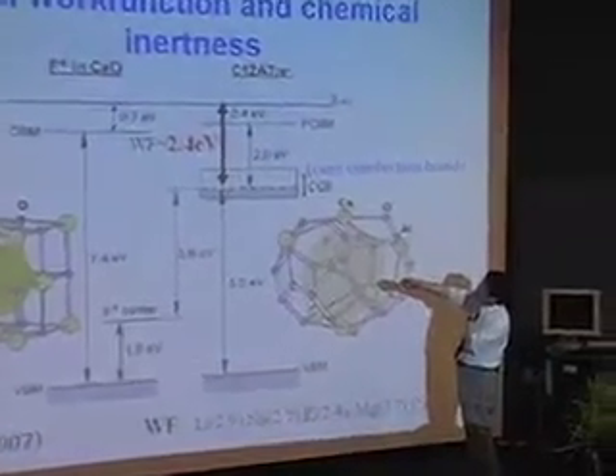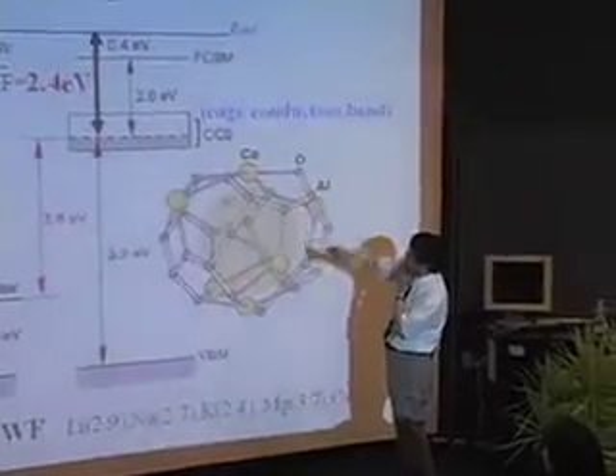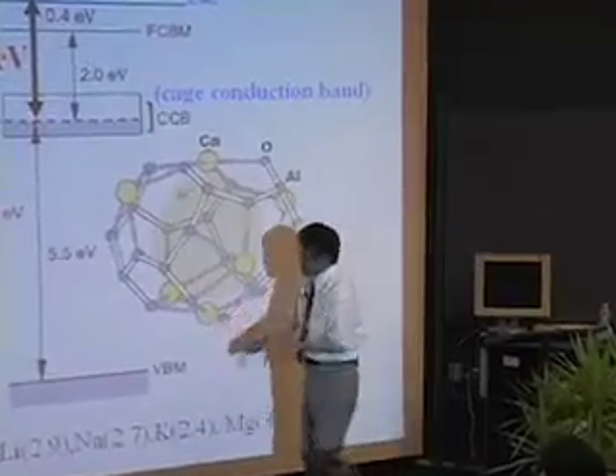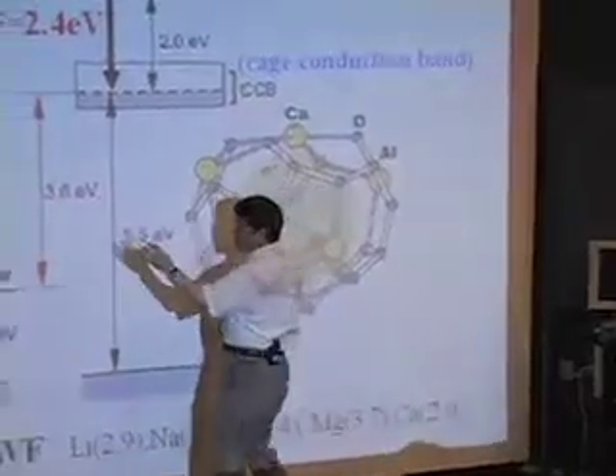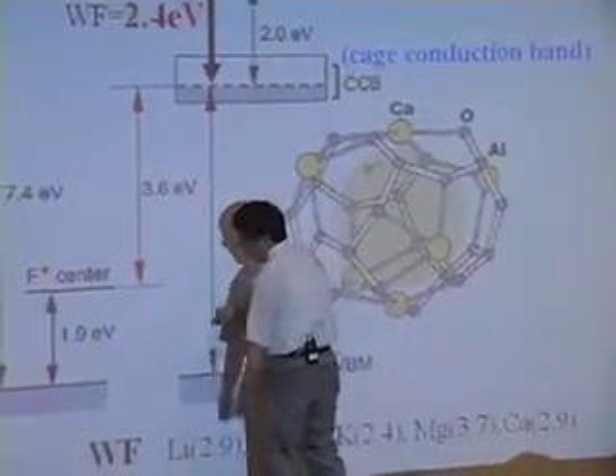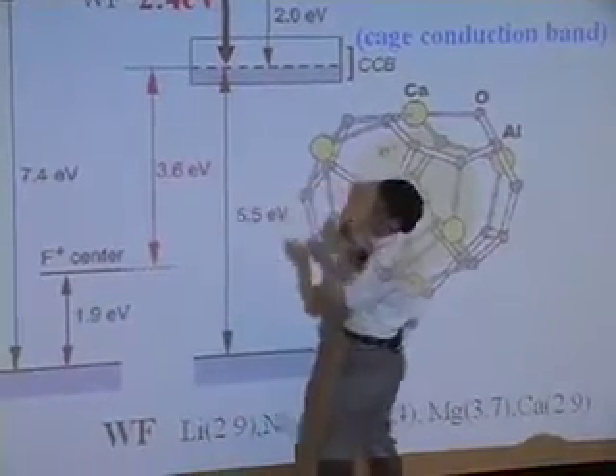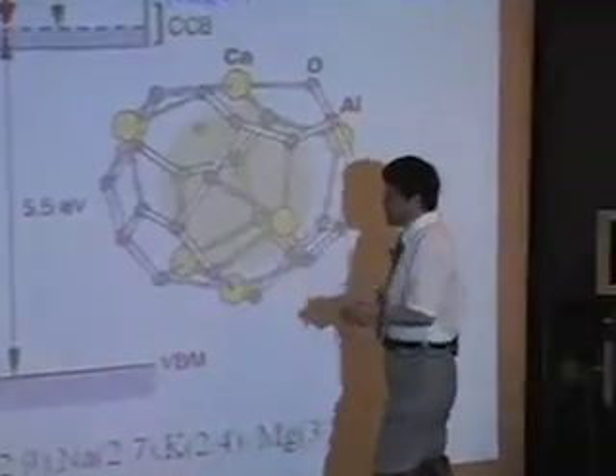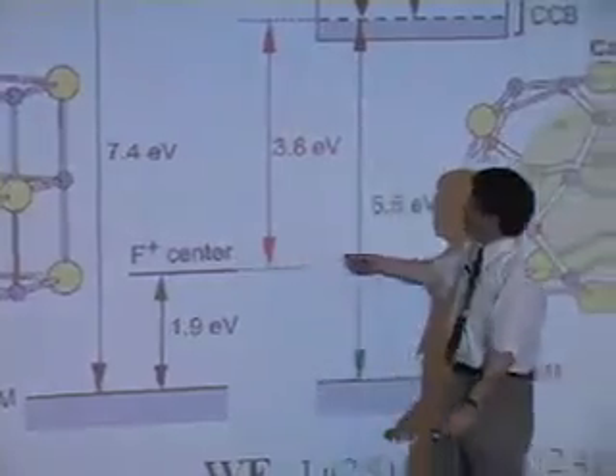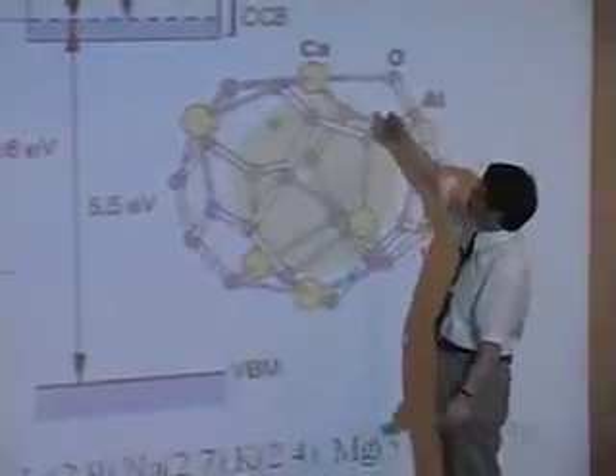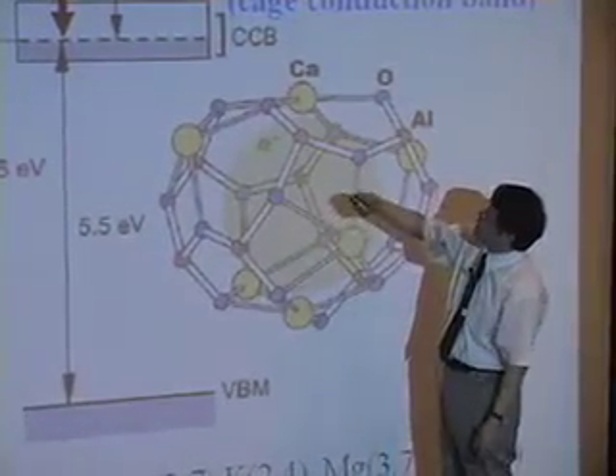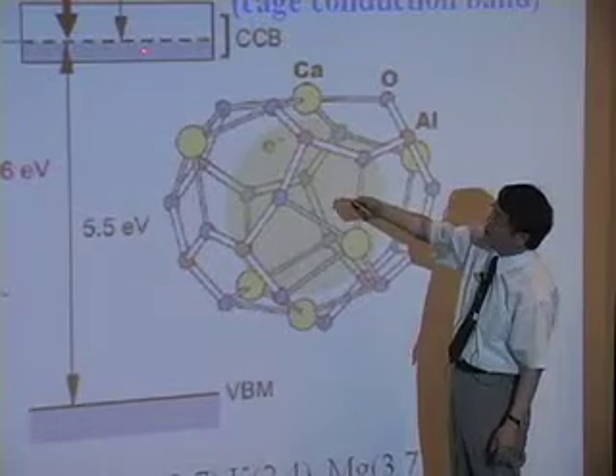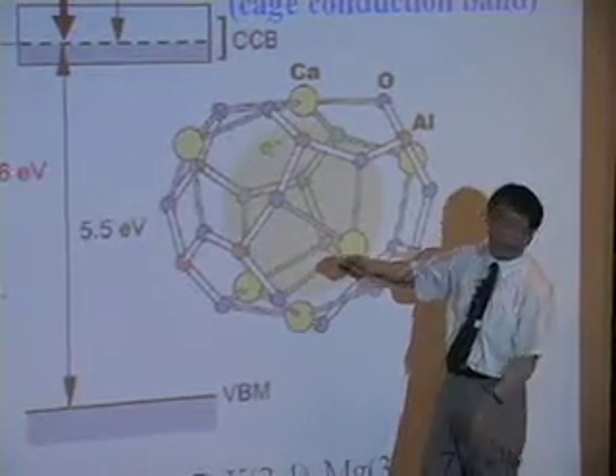The vacuum level is the same, and the conduction band bottom is here, and valence band maximum is here. So both materials are the same as band structures, except the cage conduction band. The electron level in CaO is here. On the other hand, the electron level in the C12A7 cage conduction band is located here, 3.6 eV higher.